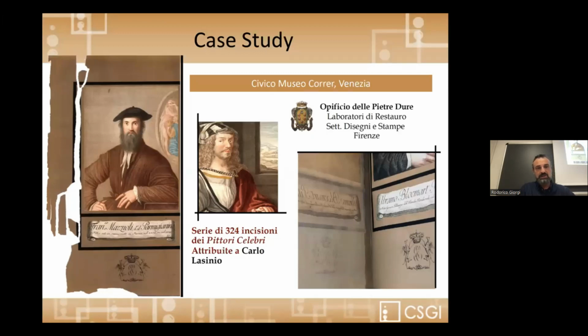I want to start with this one because this is a very precious collection of painted drawings, glue on paper. And as you can see, the paper is strongly oxidized and very, very damaged, with extremely low pH. This work was done at the Italian Institute for Conservation in Florence, Opificio delle Pietre Dure. And here the protocol was defined and applied, even for paper so degraded and oxidized, to reach a pH that was acceptable for the conservation of the original drawings on top of it.